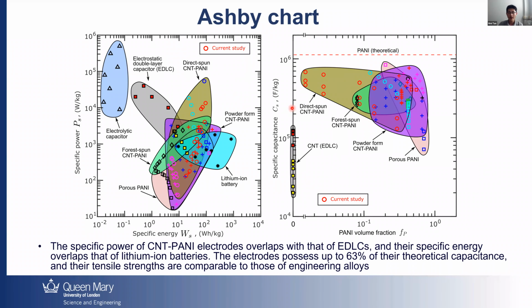And where are we in the material chart? After finishing the test, we plot our data into the material chart. The red circle is our data. So you can see it spanned along this map, and the specific power and specific energy is actually overlapping with lithium battery and supercapacitors. And if you look at the other side, our electrode, these red circles, possess up to 63% of the theoretical value of PANI. And the tensile strength, as we mentioned before, is comparable to those of engineering alloys like aluminum alloys.